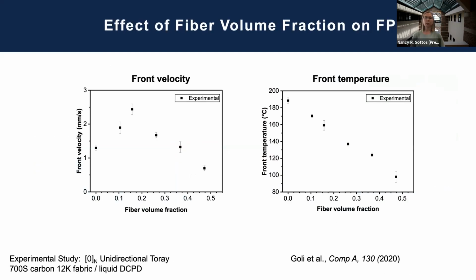So it looks like everything's working well in the video, but there is an important effect of adding fibers and other fillers to the frontal polymerization process, because every time you add filler, it is not reacting, it is not generating heat. So you're taking away monomer that generates the heat necessary for processing. And so if we look at a plot of front velocity as a function of fiber volume fraction, you can see initially as we increase the fiber volume fraction to say 20%, there's actually an increase in front velocity.